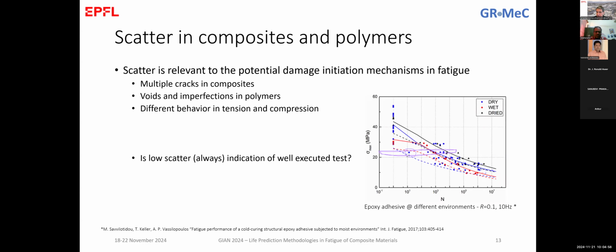If you remember yesterday, the data set that I presented with the adhesive material that we tested with 3 different types of specimens, there, for doing a comparative study between the materials, we only used what we called in this publication the cleaned data. So data where we removed this type of failures. It might be that this specimen didn't show any peculiar behavior, didn't fail in the tab, for example, or didn't fail because there was an obvious huge void in the bulk of the material, but still it does not follow my statistical distribution; it's below my statistical distribution. So this data point should not be considered in the statistical analysis. This is a data point that is censored. We call this a censoring technique.